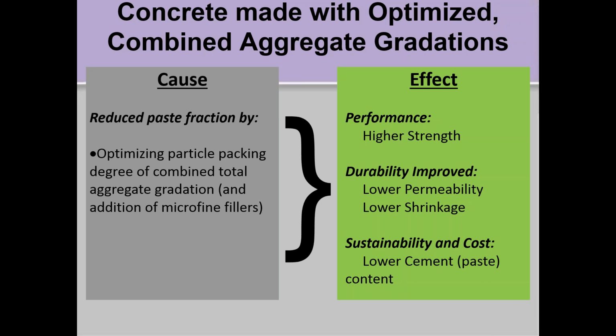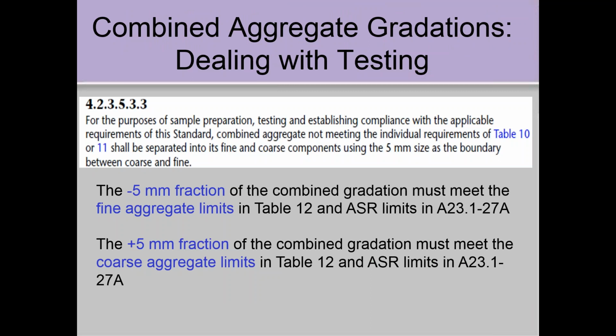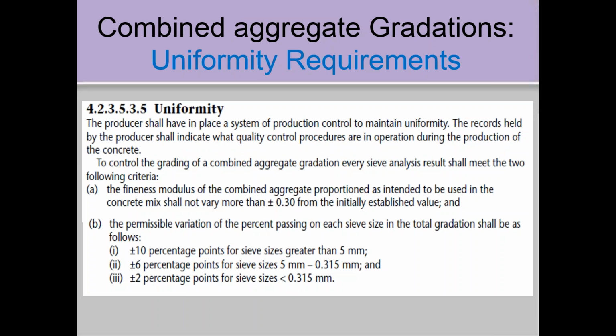And again, you can get higher strengths, lower permeability, lower shrinkage, and better, more sustainable concrete because you're reducing the cement fraction and lowering the paste content. Anyway, there's the split, and you test according to the aggregate tables based on the plus or minus 5mm fraction of the combined aggregate. So anyway, it's out there. I'm not sure how many people have tried it, but it offers an opportunity to reduce cement content in concrete and make better quality concrete. And there's some uniformity requirements to check that you're getting a uniform combined aggregate gradation, based on, at the bottom there, that the sieve fractions don't change more than a certain amount over time.